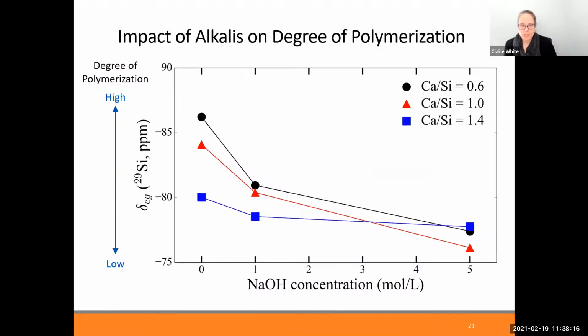If we look at a range of gels with different starting compositions and we plot this center of gravity value that we extract from the spectra, what you can see is when there's no sodium incorporated, we have relatively high degrees of polymerization for the silicate chains. But the more you incorporate sodium into the system, the more depolymerized those gels become. We knew what was going on around here, but the new information that we've really contributed is what's going on at really high sodium amounts. You have to be careful when it comes to sodium, because we are seeing quite a change between medium sodium levels and very high sodium levels. So we want to be avoiding the types of gels that precipitate at these really high values. And I'll talk in a little bit about how we're going about doing that.